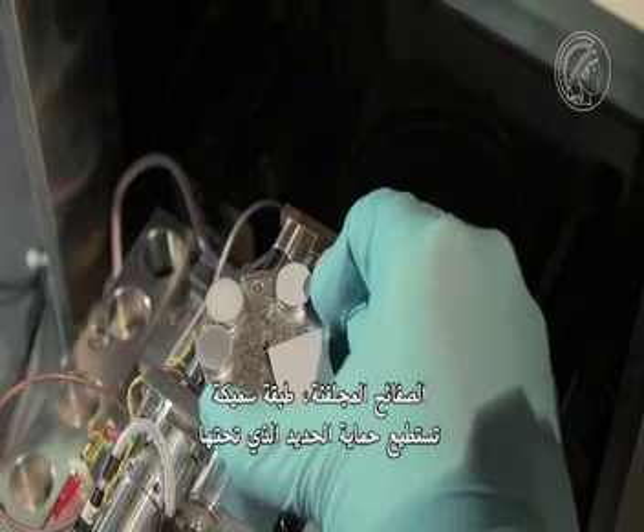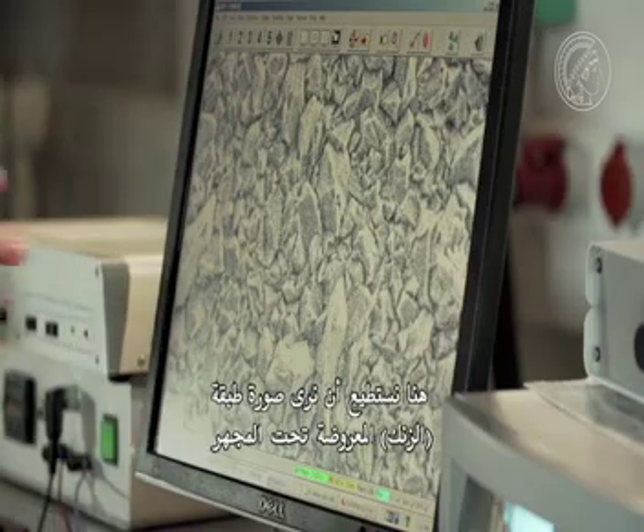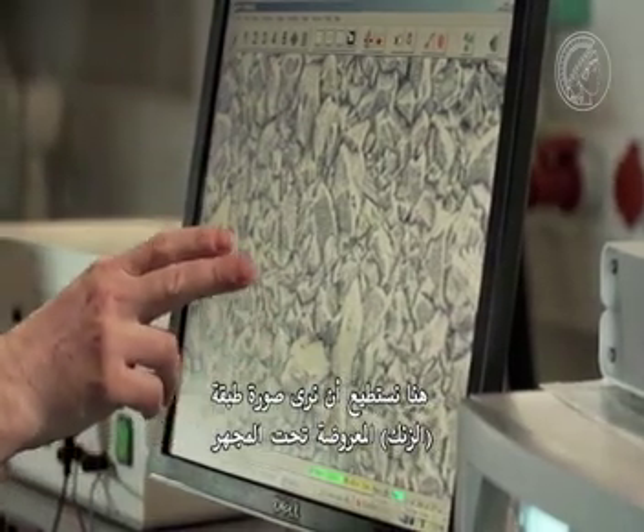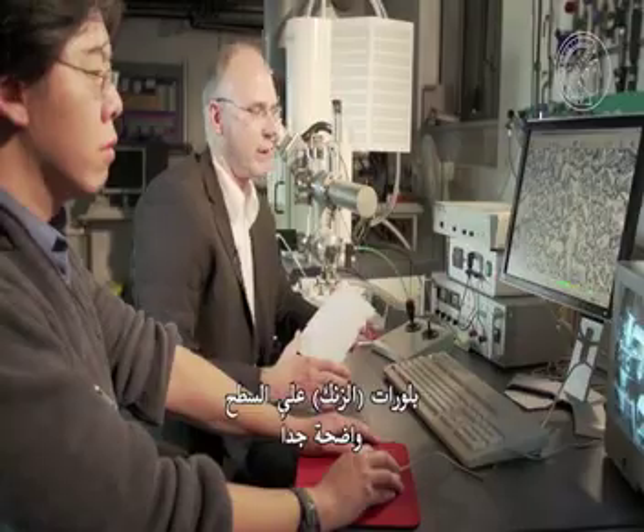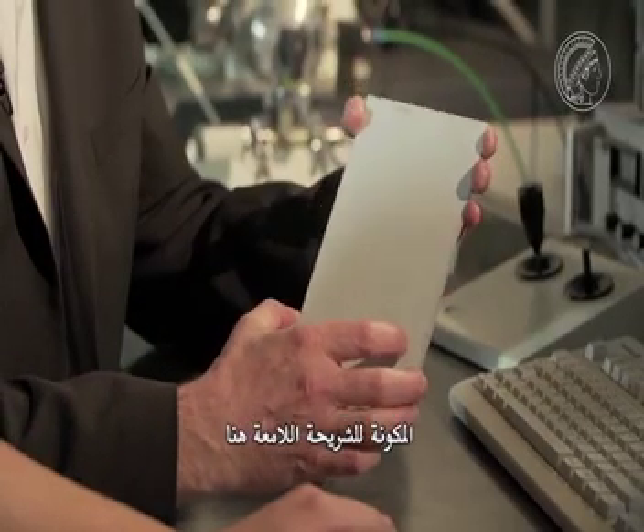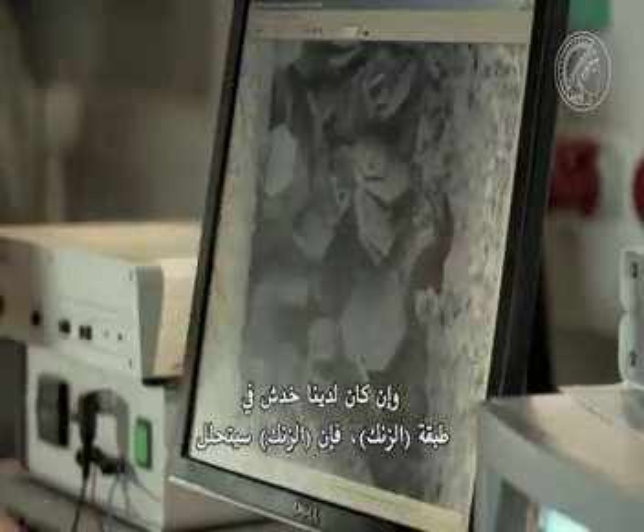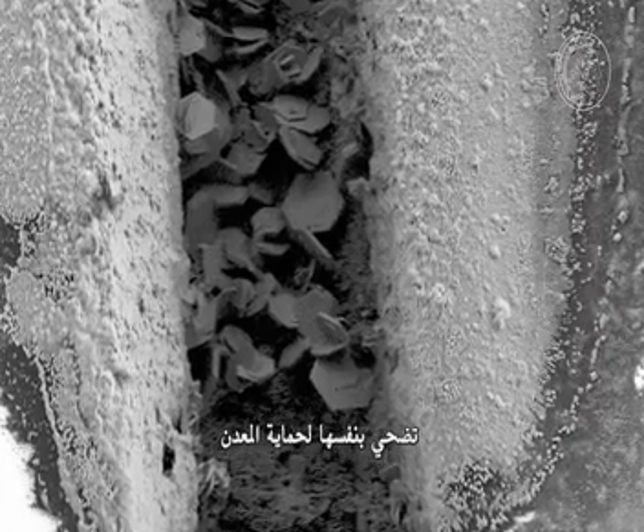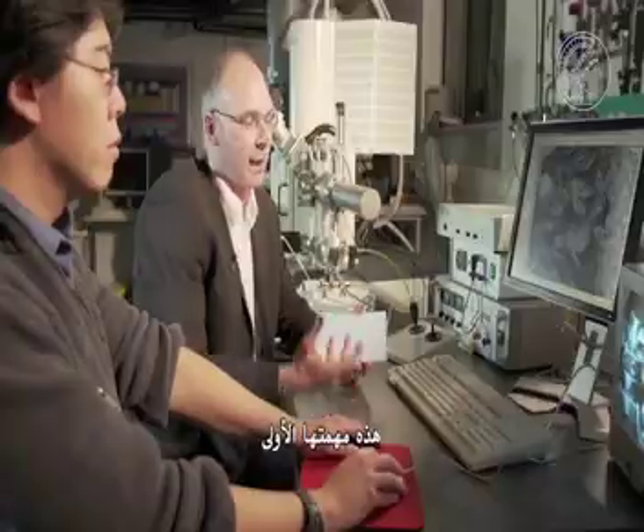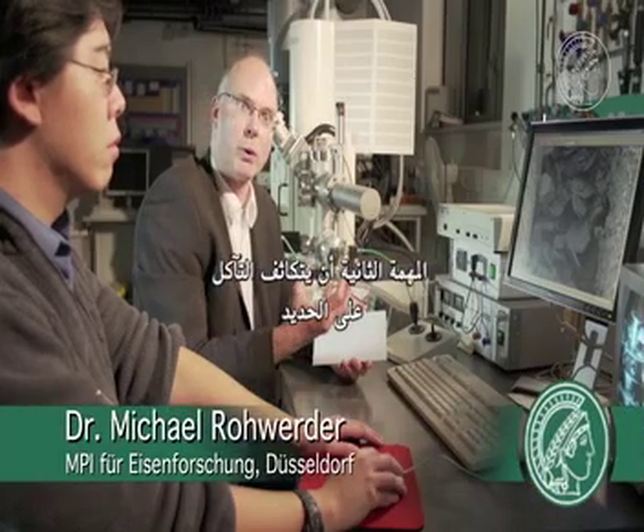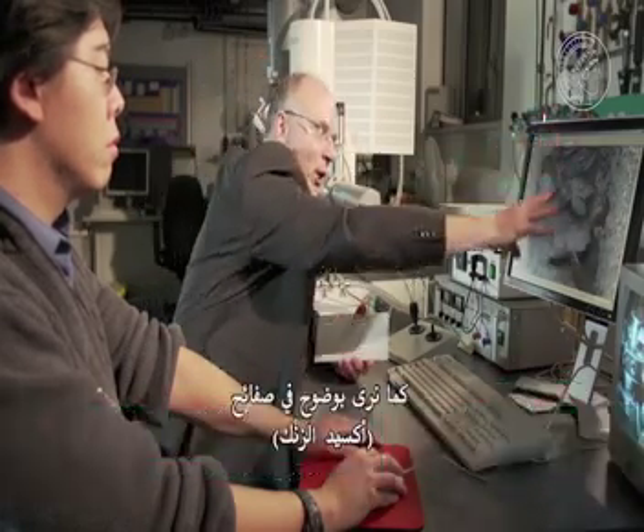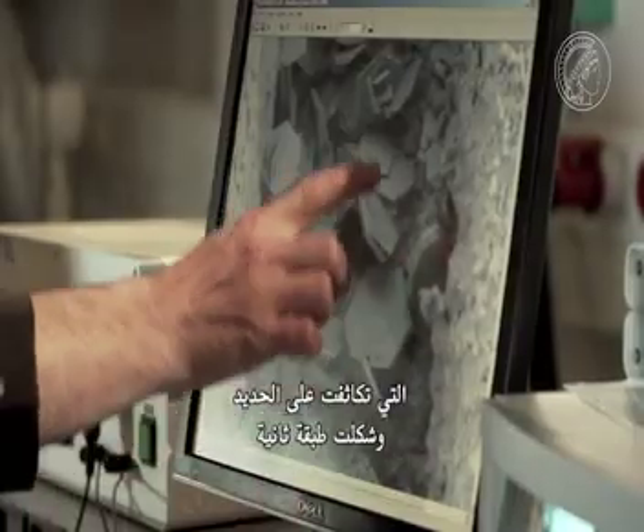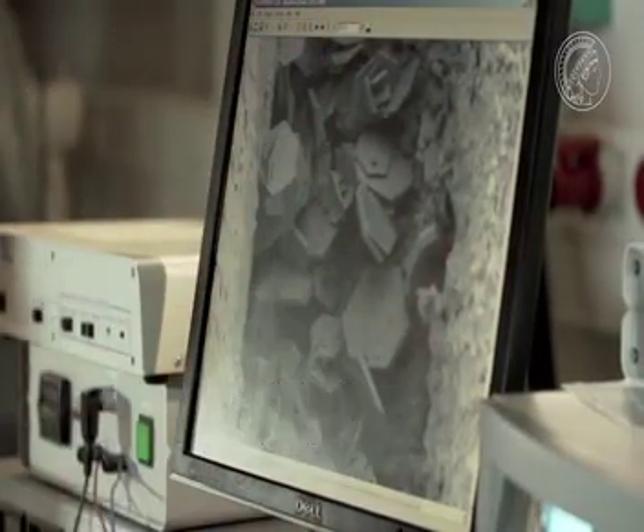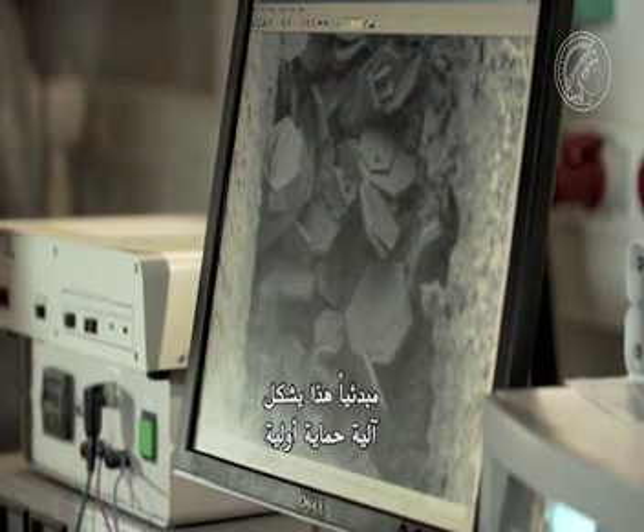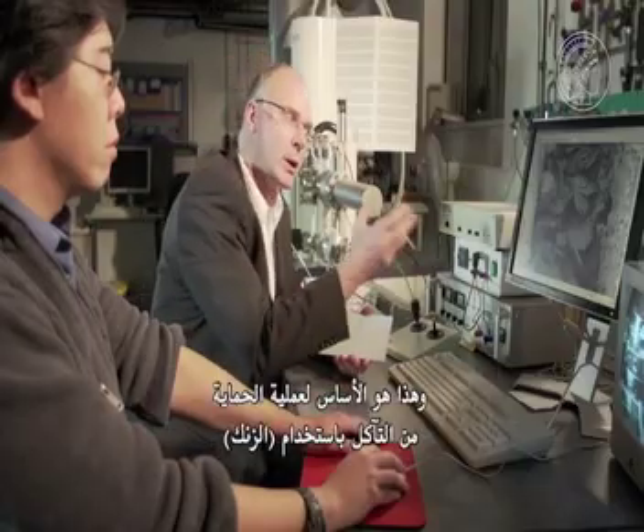Galvanized surfaces. A fairly thick layer can protect the iron beneath. Here we can see a picture of the zinc layer viewed through an electron microscope. The zinc crystals on the surface are clearly visible. They produce the matte sheen we have here. And if we have a scratch in the zinc layer, the zinc will disintegrate. It sacrifices itself to protect the steel. That is the first function. The second function is that the corrosion products condense on the steel, as we can see clearly in these zinc oxide platelets, which have condensed on the steel and formed a second skin, in principle thus providing a first protective mechanism. And that is the basis for the corrosion protection using zinc.